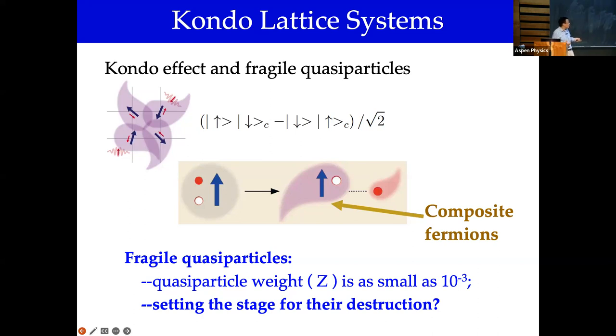And so these are quasi-particles. They're very fragile. The quasi-particle weight is 10 to the minus three. If we were able to do spectroscopy, as I illustrated, the area under that peak would be 10 to the minus three of the total area of the entire electron. It's already very fragile. So perhaps we can break this dictate of the perturbation theory that I mentioned, that made the quasi-particles resilient. If to begin with, quasi-particles are already so fragile, maybe they can be destroyed more readily. That's where this small parameter comes into play to give a good starting point.